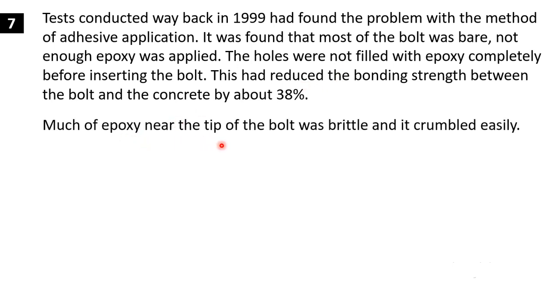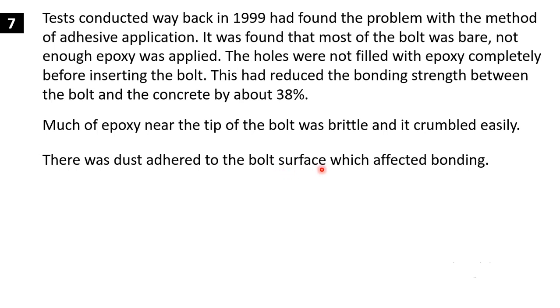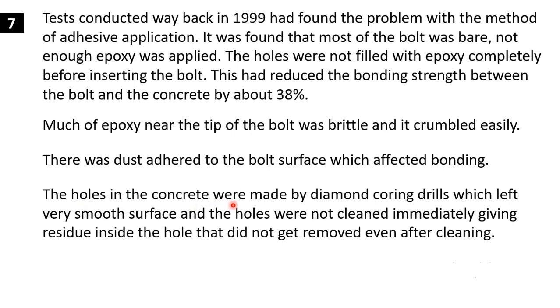Much of the epoxy near the tip of the bolt was brittle and it crumbled easily. There was dust adhered to the bolt surface which affected bonding. So again, any surface which has to be bonded must be very clean and there should be no dust particles there. The holes in the concrete were made by diamond coring drills, which left a very smooth surface, and the holes were not cleaned immediately, leaving residue inside the hole that did not get removed even after cleaning.